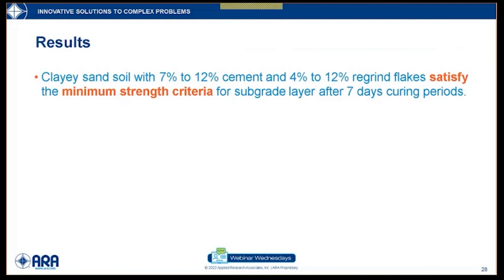The results of the UCS test show that the soil with 7 to 12% of cement doses and 4 to 12% regrind flakes satisfy this minimum strength criteria of the subgrade layer when cured for 7 days.